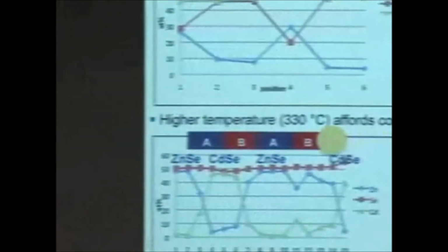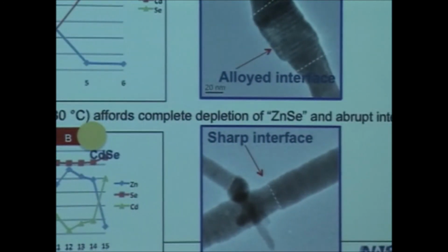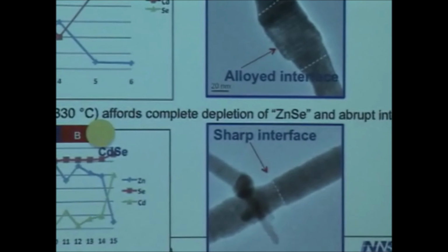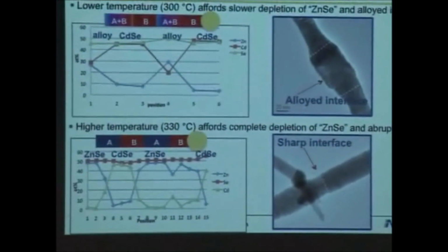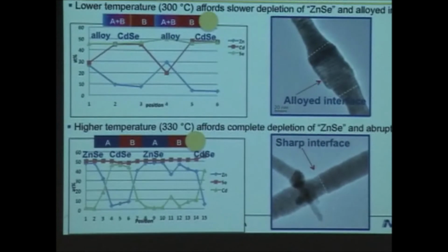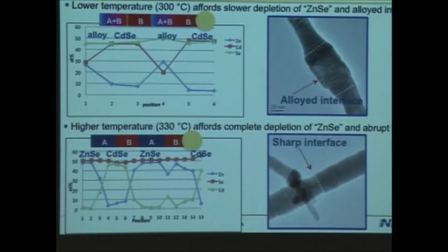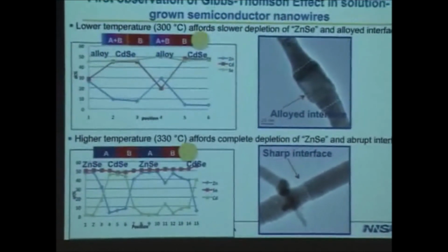So the catalysts are staying the same size. You don't see some sort of ripening effect of the catalyst, so it gets to a critical size before the growth starts to take off. No, we definitely see some. That's the induction time. And then you can see that the alloy interface, the alloy region, is often fatter than the pure phase regions, and I assume that's just because we've swollen the catalyst with the other phase. It seems to happen quite a bit, yeah. Not constantly.